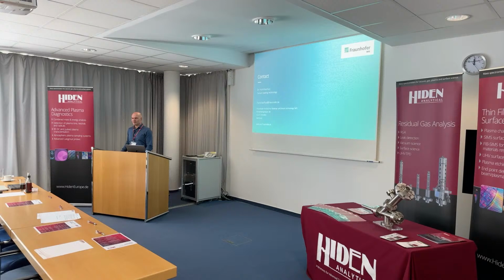I also have a question regarding adhesion, but in the measurement system. Since you have carbon plasma, basically that we also have sometimes in our environment, and we have seen some issues with the deposition of carbon materials inside the EQP system. So is this an issue also? We haven't looked at the inside. We sent it back to the colleagues, and they sent it back to us and said there's no problem at all. Everything is still conductive. But yes, if you have highly ionized carbon, then you have some non-conductive films generating, and you need only a few nanometers, and then you have no connection anymore. But this was not a problem.